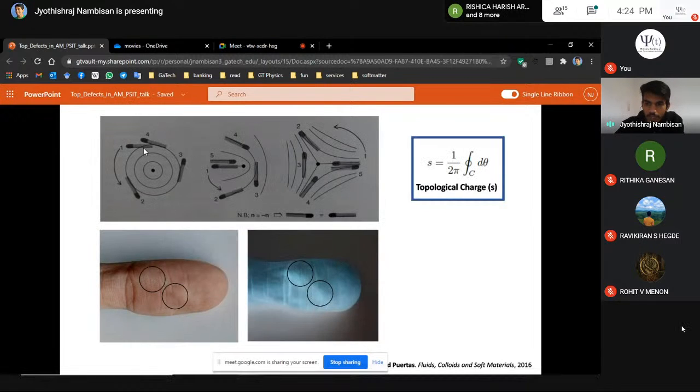So how exactly do we calculate the topological charge? Just by a simple example here. Imagine a matchstick which is actually head-tail asymmetric. So there is a head and a tail, and you move this matchstick or pin or whatever along the director field, and when I go around a contour by 2 pi, I end up in the same configuration. So this measure is 2 pi over 2 pi, which is plus 1. But when I translate it along the director field around this defect, I actually end up with the opposite configuration when I go 2 pi.